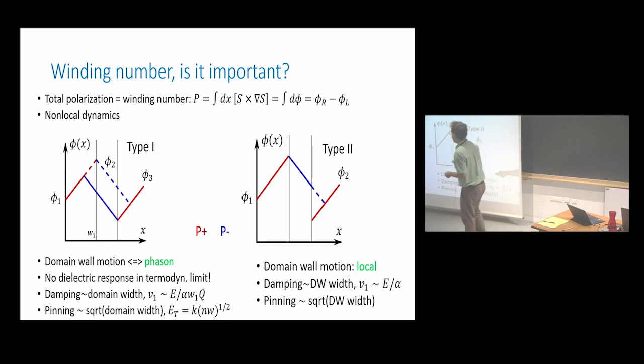Then the dynamics. Let's look at this type 1 wall. Spins are rotating clockwise, then counterclockwise, then clockwise. So what type of dynamics can I do without breaking this curve? For example, I can move this blue segment to the dashed position. You see that the system is characterized by these phasons. I cannot break these lines. I cannot change the Q vector; that will cost me in terms of J1, J2. But what I can do is move these segments up and down.